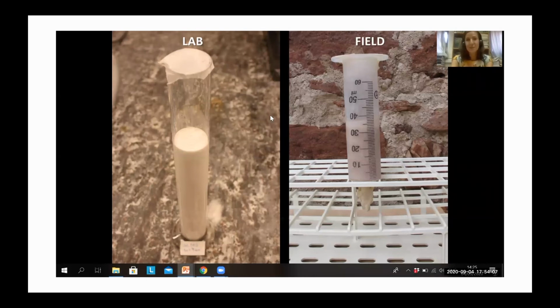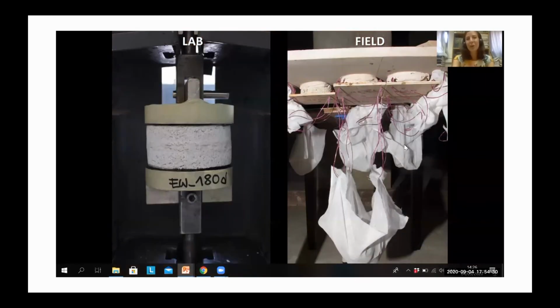Or you can have this one, for example, which is concerning bleeding. So how much the solid and the liquid of the grout divide one from the other. Again, you have the lab version with a graduated cylinder, or the field test version just with a syringe with the tip blocked. Or for example, this test of adhesion: this is the laboratory version involving a mechanical testing machine, giving you a very specific number in terms of adhesive strength, or the field version with the preparation of the sandwich, and the assessment is still a quantitative assessment because you calculate the strength according to the surface and the weight you add, but still, of course, it is far less precise.